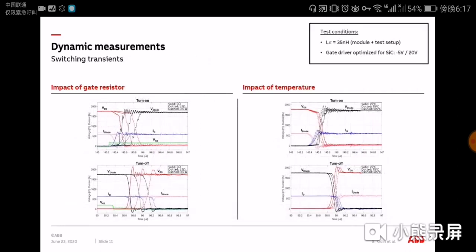A double pulse test was used to investigate switching performance of the module at different operating conditions. Inductance of the test setup was about 35 nanohenry, including inductance of the module. A gate driver developed for silicon carbide modules was used in the test. Slide 11 illustrates the impact of gate resistor and temperature on switching transients. Observed ringing is reasonable for the applied test conditions.